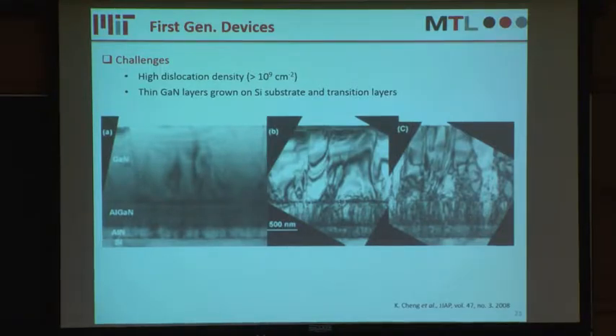The second challenge is due to the lattice mismatch between the silicon and the gallium nitride, the total gallium nitride layers that can be grown on silicon substrate and transition layers are relatively thin, typically limited to 4 to 5 microns.